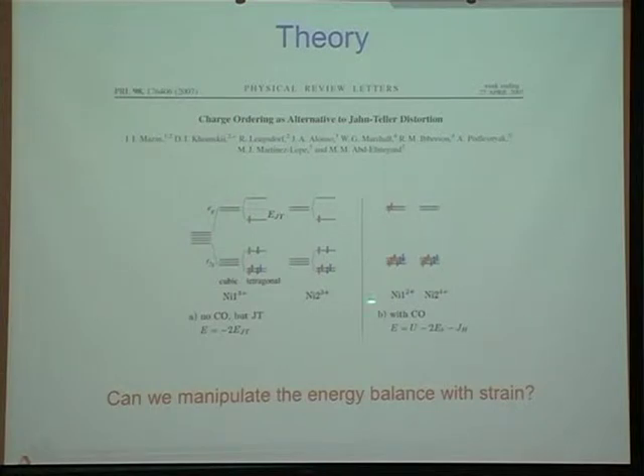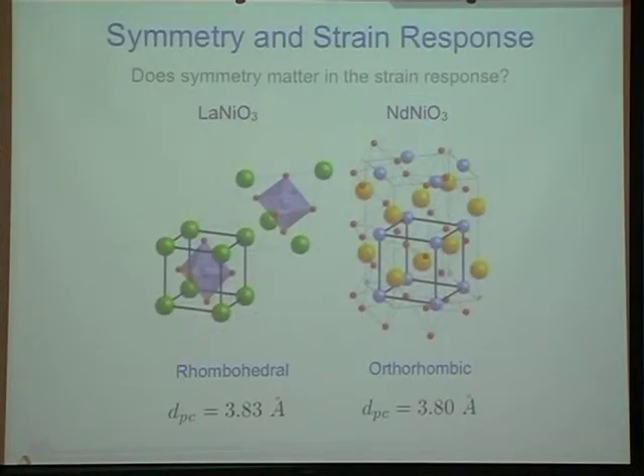And so it turns out if the conditions are just right, even though you have to pay a U to put 2 electrons here, if you gain a lot in the breathing mode, then basically you could stabilize this kind of bond disproportionated state. So then the question is, well, if I can use strain to control this distortion of the octahedra, maybe I can play a game between these. Maybe I can use strain to move between one and the other. So the first question is you have to learn about what strain does.